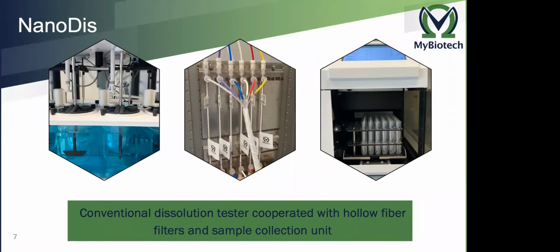That is the reason why we developed this system. It's called NanoDis, together with Agilent. It has three different parts. The first part is a conventional USP 2 dissolution apparatus. We don't want to really change anything there, because it is an accepted apparatus which is widely used for R&D and for quality control purposes. Also, it is already in the pharmacopoeia. It is also accepted by the authorities.